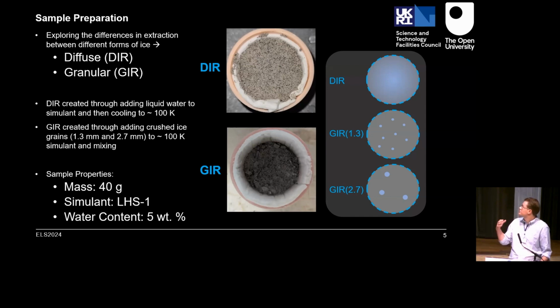The whole idea was that this is the permafrost technique, which had quite a lot of heritage. It's got quite a few papers and people looking into using it this way. And then I also created cryogenic ices and crushed them using a hammer, then sieved them through cryogenic sieves to get to a particular size range. I made two different ice grain sizes for that. And again, you add it to already cold simulants so that the ice grains don't remelt, and then try and mix them as well as you can.